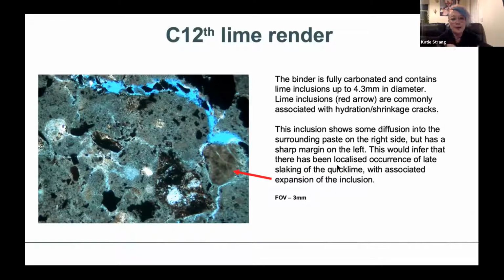Now, when you're looking at that, one of the things you want to do with your analysis is try and work out what the mix proportions are. If anybody's ever done any building or built a wall in your garden, you'll know that with lime or cement, you normally have 1 part of lime to however many parts sand. So that's another thing that we try and deduce from these thin sections. But for this particular lime inclusion, the cracking around it normally indicates that it's actually undergone slaking while it's been placed within the mortar.